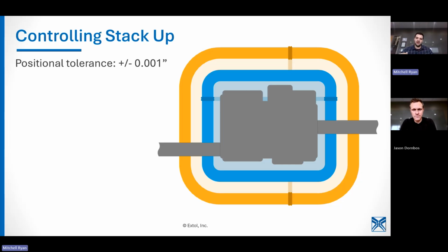All these tolerances stack up on themselves. The position of our platens is controlled to the thousandth. You probably want to assume a little more for the stack-up because you've got some part inconsistencies with plastic welding, but we can pretty reliably hit plus or minus 5 thousandths because we're planing those parts flat, even with inconsistent parts.